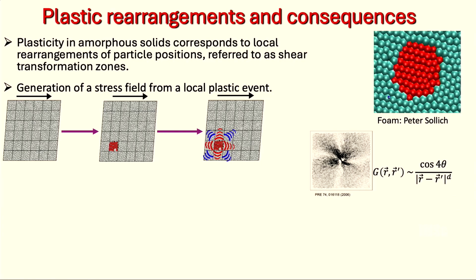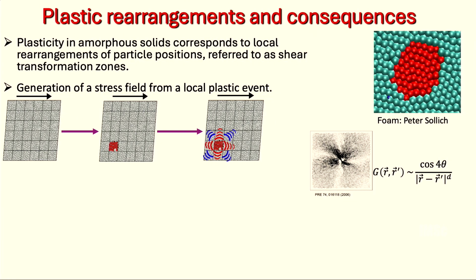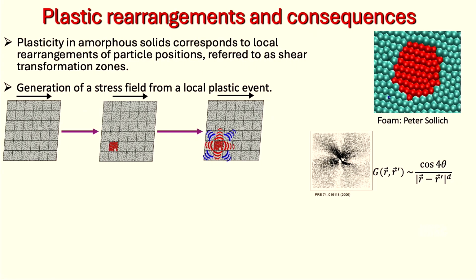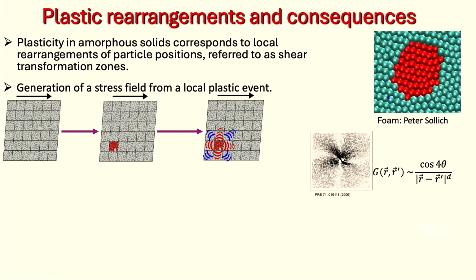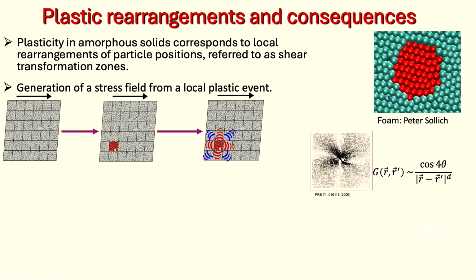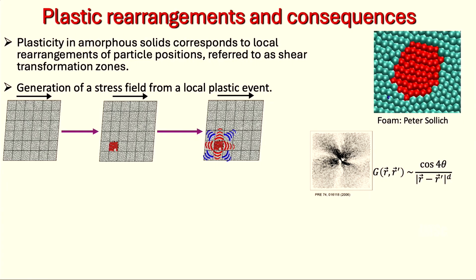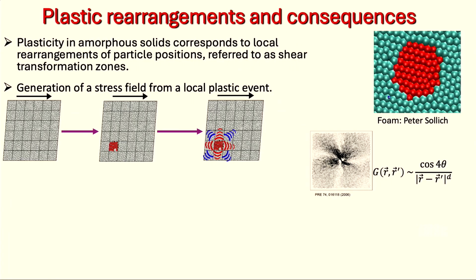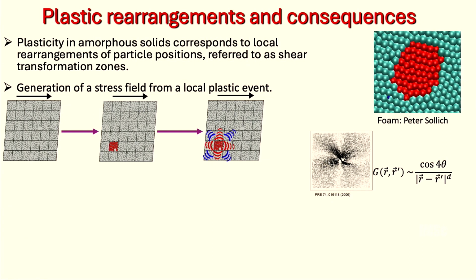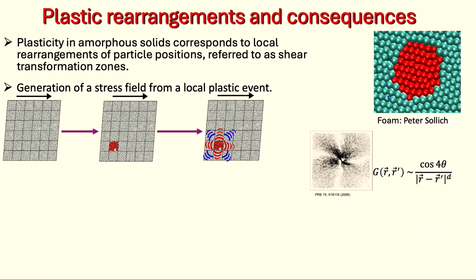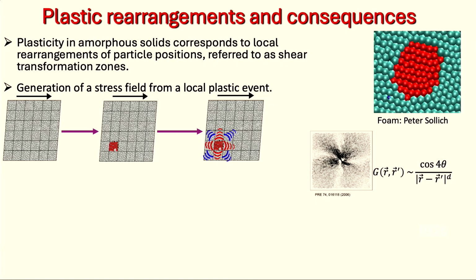an amorphous solid, this leads to the propagation of stresses in the surrounding solid, and this is something that people have discussed a lot and understand. It has 1 over r to the d variation with distance and spatial anisotropy of the form that's shown here. But the basic idea is I can think of my amorphous solid as made up of mesoscopic sized blocks within which I can think of how to describe plasticity. And then anytime there is a transition that corresponds to a plastic rearrangement in one of these mesoscale blocks, it has consequences in the form of stress propagation to the other blocks, okay?